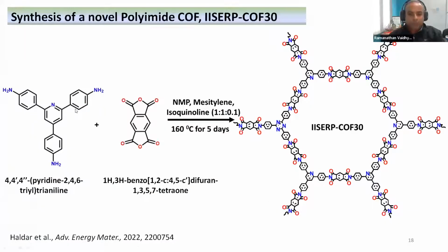And here is what we did. We took a COF. It is not like you can use any COF, because these capacitive studies are done in highly acidic medium, which means your COF should have a high degree of stability. So considering this, instead of going for a simple imine COF, we have gone for an imide COF with cyclic rings. And this really gives a chance of a high degree of stability under the demanding conditions.